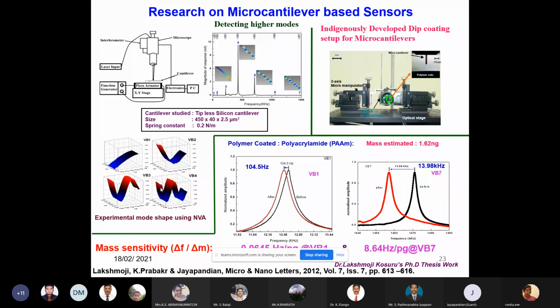Further, what we did, the right side is a coating system we fabricated. It's simple. With a motor movement, we dip the cantilever in a sol gel solution, then remove it and dry it, then we have a coating. Before coating, monitor the resonance frequency. After the coating, drying out, monitor the resonance frequency. Now, what is the difference? After coating, mass is added to the cantilever, then the expected resonance frequency shift. That's what you can see in the graph, black color and red color. Black color is the virgin, without any coating. Red color, after coating.